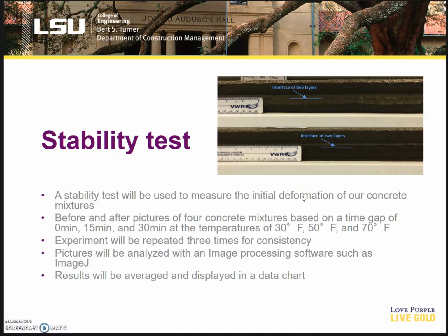How we'll test this will be through the stability test. The stability test will be used to measure everything. This is before and after pictures, essentially. We'll be using a ruler as a benchmark. What you do is you print out an initial layer, and the second layer will be placed based on one of our time gaps, which will be at 0 minutes, so immediately after, 15 minutes, and then 30 minutes. And this will help establish our initial stability for each layer.